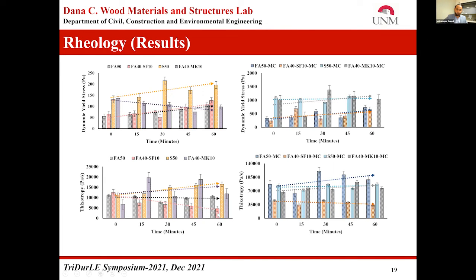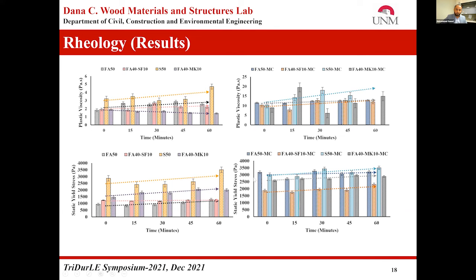Thixotropy is a very important property when we are dealing with 3D printing of cementitious material. It is the structural recovery of the material with respect to time at rest. The thixotropy was significantly increased, and this could be attributed to methyl cellulose, because it has water retention capacity and the potential to increase the plastic viscosity and the thixotropy. Similarly, the methyl cellulose particles can adsorb on the cement particles and bridge them, and this phenomenon can lead to modification of the static yield stress.